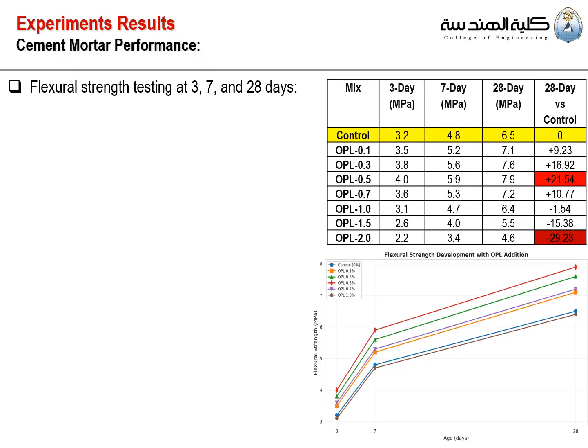On this slide, we will present the flexural strength testing for the 3, 7, and 28 curing days. As you can see from the table, the control base has a flexural strength of 3.2 megapascal at 3 days, 4.8 at 7 days, and 6.5 at 28 days.